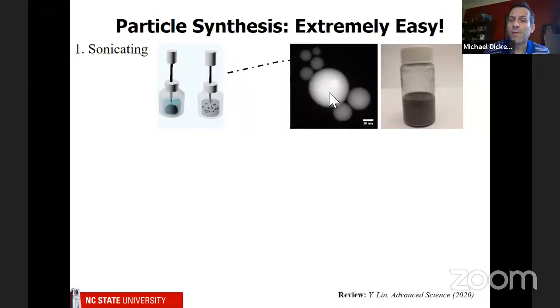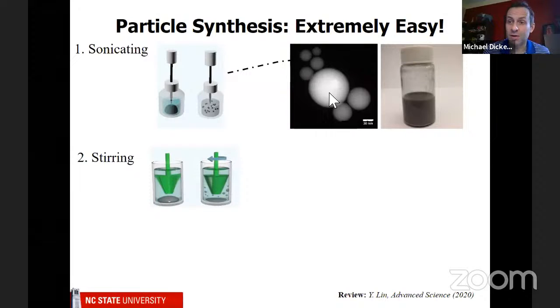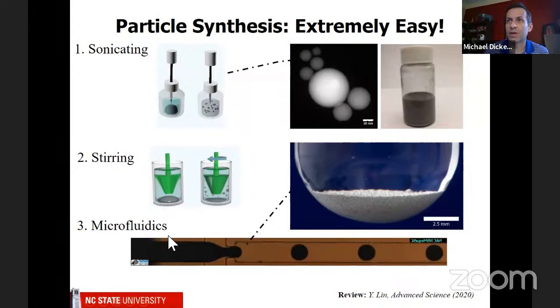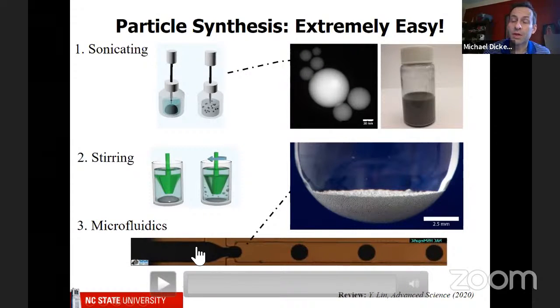nanometers or so. Another way to do it is just by stirring, very aggressive stirring. This is called a high shear mixer, which just stirs very fast. And then another way to do it is by using microfluidics. And so we've done some work here where we're pumping the liquid metal. So the liquid metal is black. And we also pump another fluid, which you can't see because it's clear.